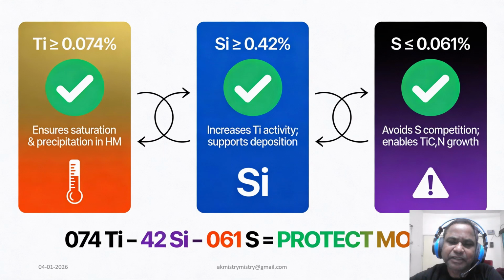Finally, sulfur, and this is one of the most important ingredients, and it must be below 0.061% to avoid competition and enable the growth of the TiCN layer. Once sulfur becomes higher, all the titanium will be consumed by sulfur, and in return the titanium carbide and nitride targeted activity will fail.